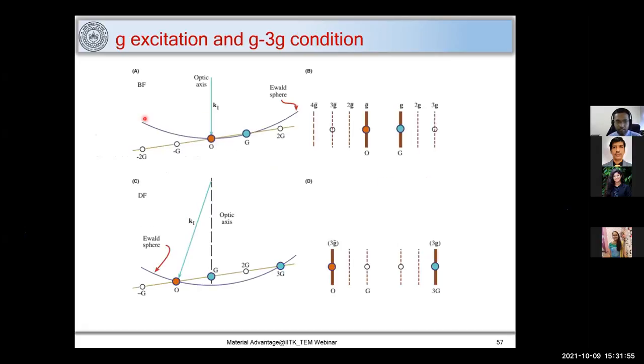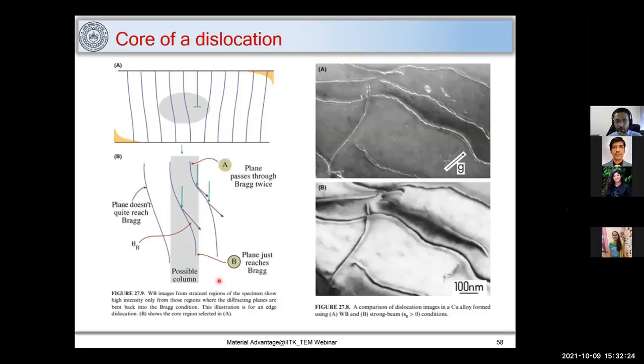So here in this case, the Ewald sphere was passing through the first G spot. When I do the G-3G condition, what is happening exactly? It passes through the transmitted spot and the 3G spot. So this G will have positive excitation error, that is S will be positive, and we image the dislocation using this spot. So this is on the optic axis, so there will not be any problem of alignment when I image the dislocation using this spot.